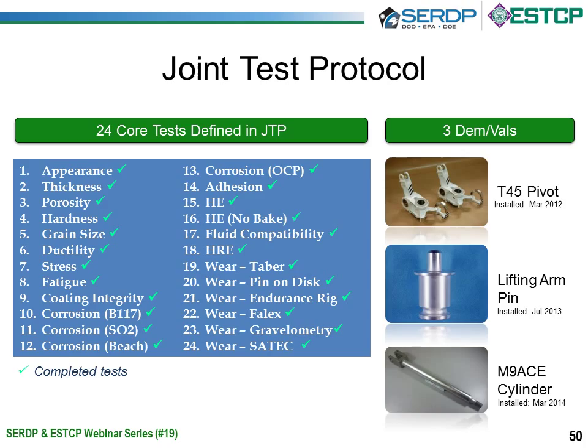In essence, the ones 1 through 6 are basically coating quality. Can you actually electroplate, produce an electroplate that meets our appearance requirements, free of porosity, et cetera, free of defects, that we could actually pass a quality assurance visual check in terms of quality. The remaining ones had to do with mechanical properties, fatigue performance, corrosion performance, hydrogen embrittlement, wear, et cetera.